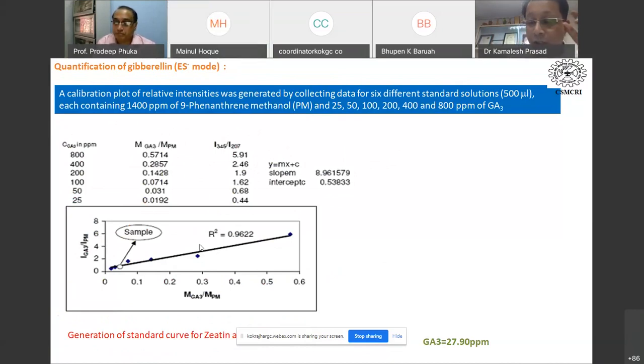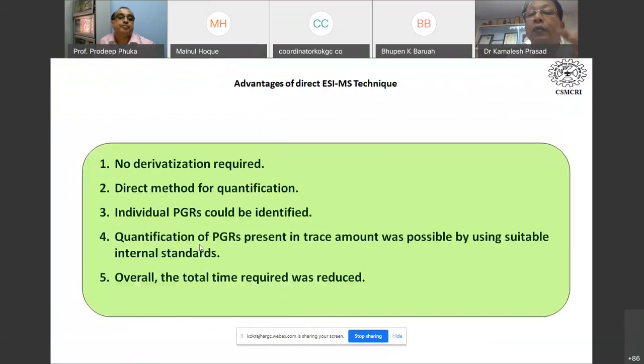So this is the reason for telling all this, that the method we have developed requires no derivatization, because if you want to analyze something by GCMS, you have to derivatize the molecule. Any carboxylic group has to be converted into esters to be done by GCMS. But in this particular case, we are not derivatizing any of our molecules. It is a direct method for the quantification. Individual PGRs, PGRs means plant growth hormones or plant growth regulators, can be identified, and quantification of PGRs present in trace amounts was possible by using suitable internal standards. The total time required was reduced. So this is the discovery, or we can say finding, we got from this method.